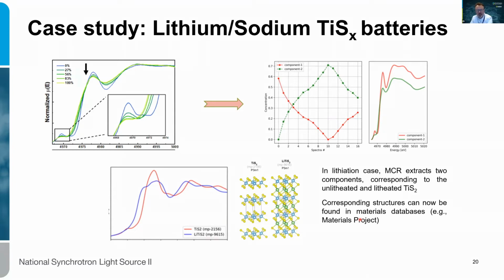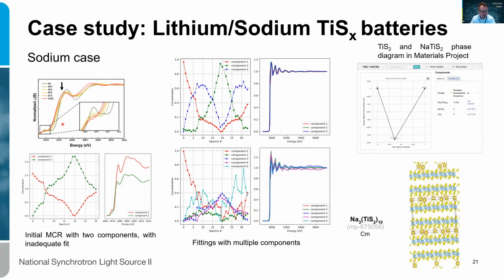Now, what happens in the case of the sodium? The two components are really not sufficient for the fit. We need to introduce an additional spectrum, and we tried the process with multiple contributions and concluded the three components are sufficient to describe the system through the charge-discharge cycle.